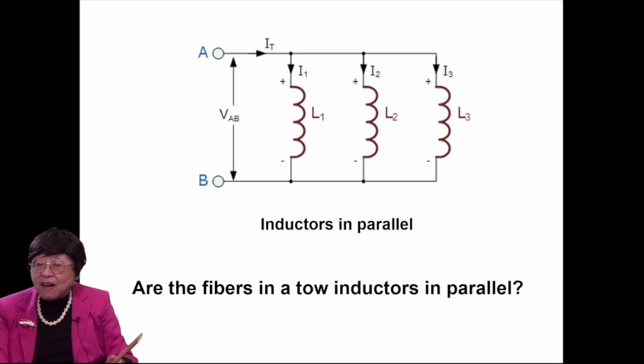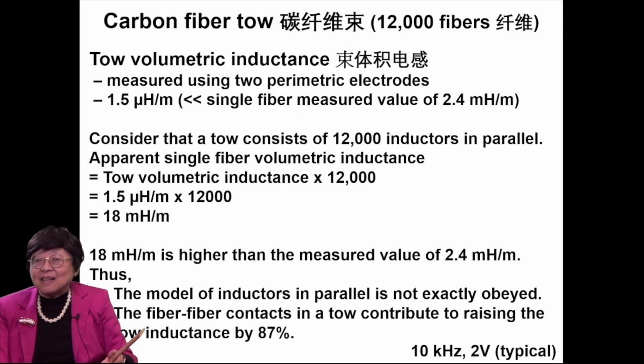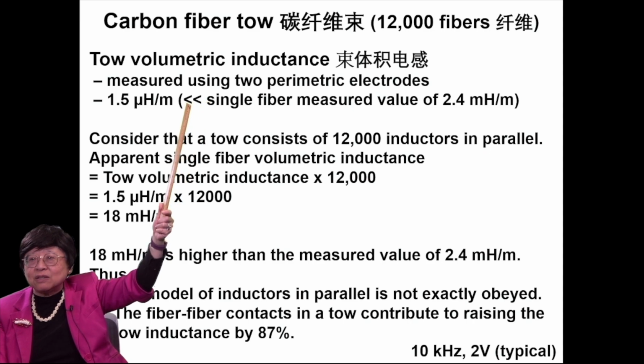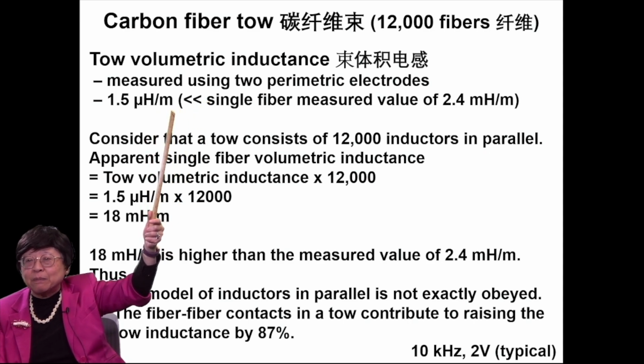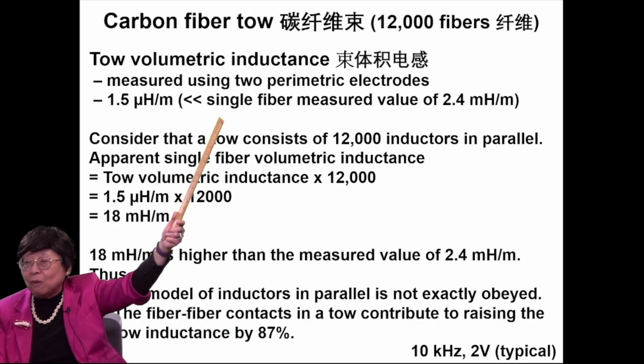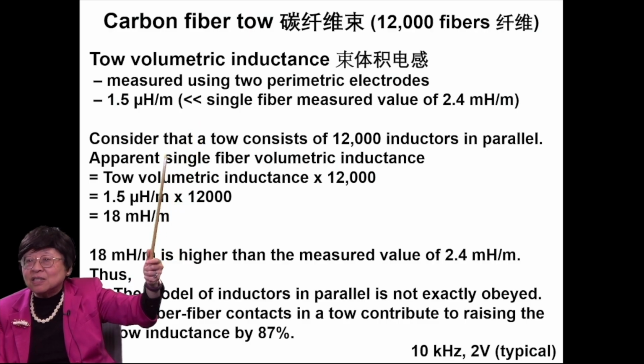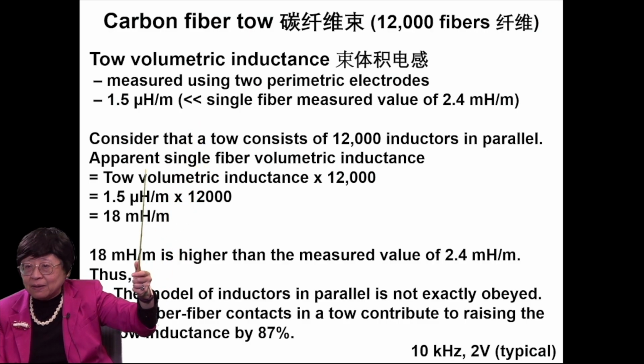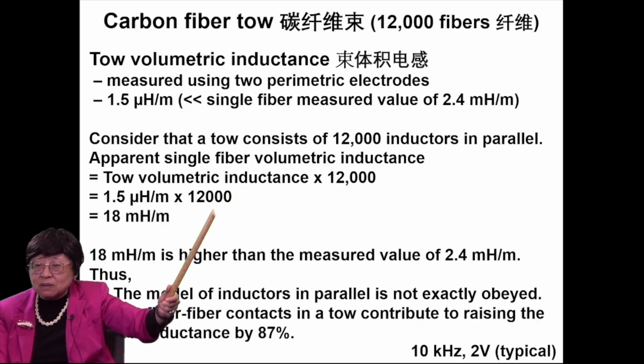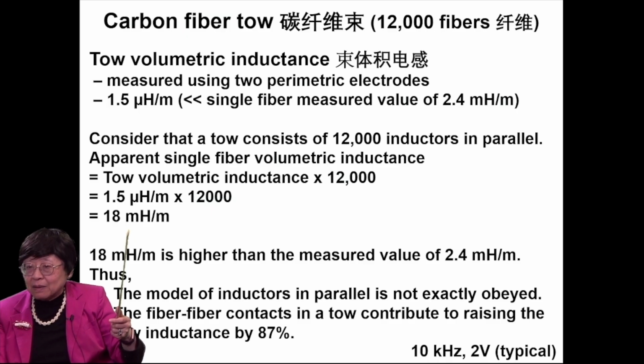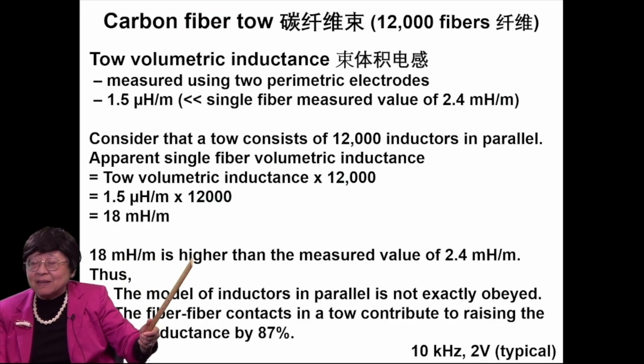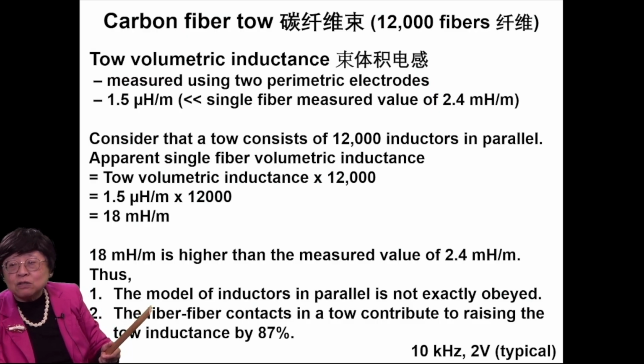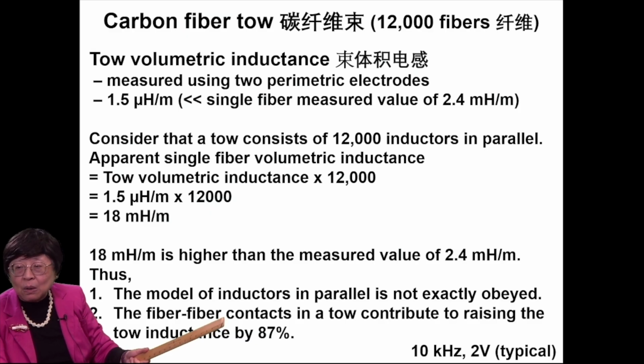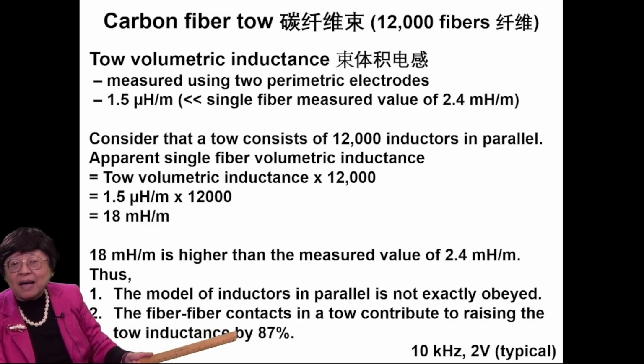Okay. The question is, are the fibers in a tow inductors in parallel? The tow volumetric inductance, measured using two perimetric electrodes, is 1.5 microhenry per meter, and that's much less than the single fiber value of 2.4 millihenry per meter, as I already mentioned. Now consider that a tow consists of 12,000 inductors in parallel. Then the apparent single fiber volumetric inductance would be the tow volumetric inductance times 12,000, and that becomes 18 millihenry per meter. But this 18 millihenry per meter is higher than the measured value of 2.4 millihenry per meter for the single fiber. Thus, the model of inductors in parallel is not exactly obeyed. The fiber-fiber contacts in a tow contribute to raising the tow inductance by 87%.